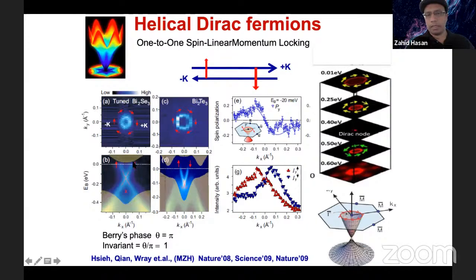So we scan this entire range, and we see that there is always this spin momentum locking anywhere you place your Fermi energy. Let's say if you're above the Dirac crossing, then you have this chirality, but below the crossing you have counterclockwise chirality. So this confirms that this is the double and this is single degenerate, and the spin momentum locking is maintained throughout the gap. And it's all happening on the surface. So then the full picture is kind of like that.